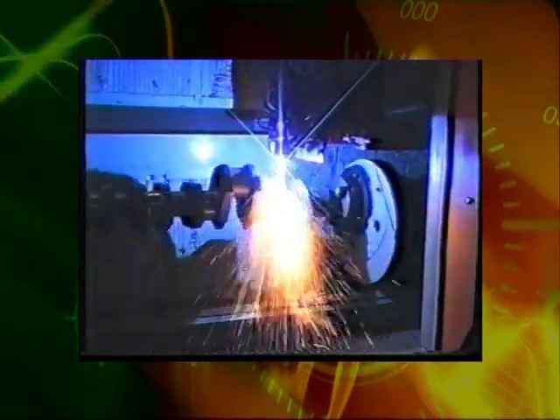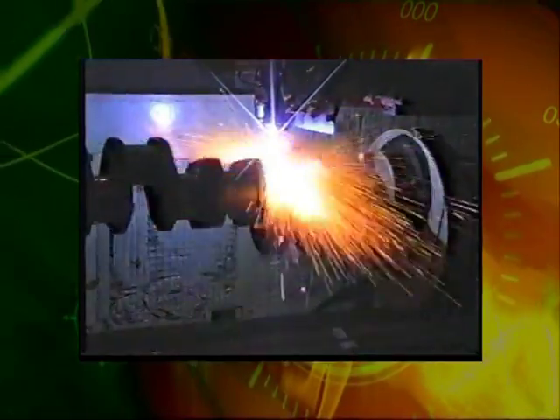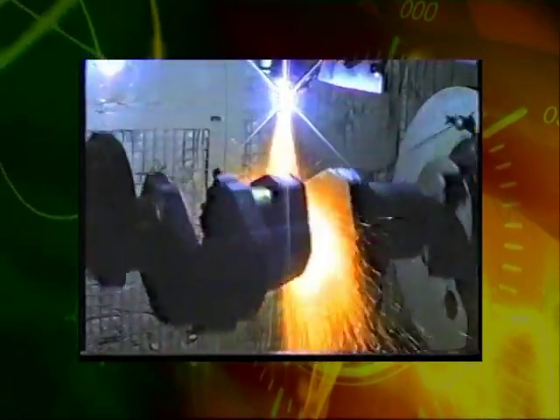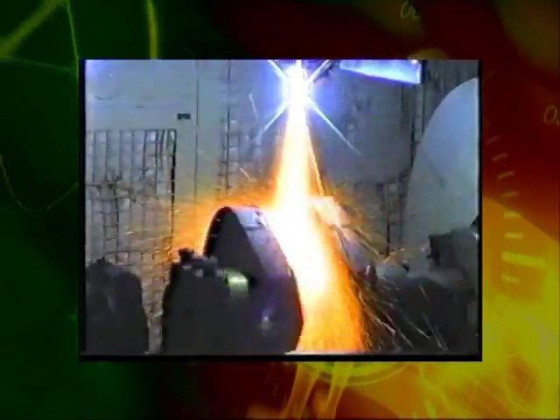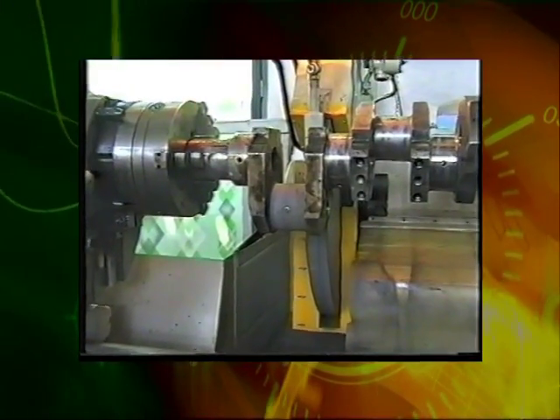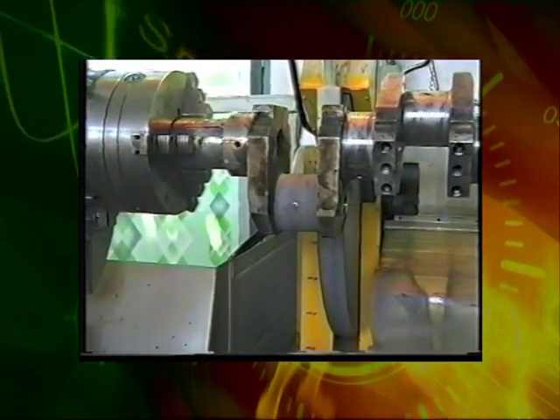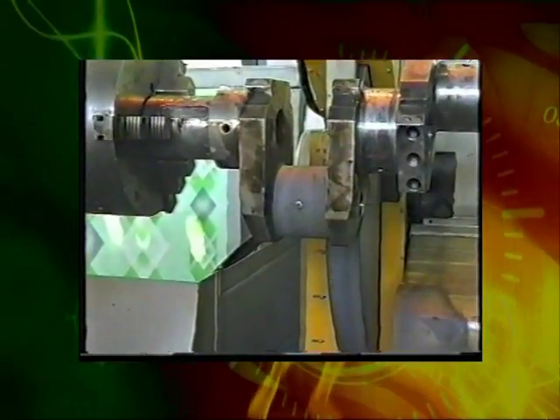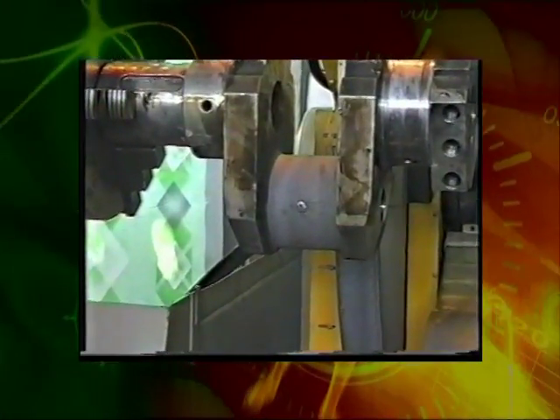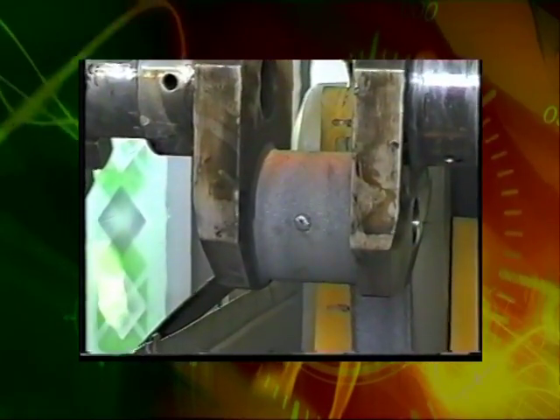The supersonic electric arc metallization machine Plazma can be applied in all typical cases where it is necessary to deposit high-quality coating. This allows heavy-duty parts such as shafts, crankshafts, brake drums, etc. to be efficiently repaired without any degradation of fatigue strength. The service life of repaired parts is not inferior to that of the new one. A new installation was successfully tested in the industry to repair worn-out motor components and deposit corrosion protection coating.